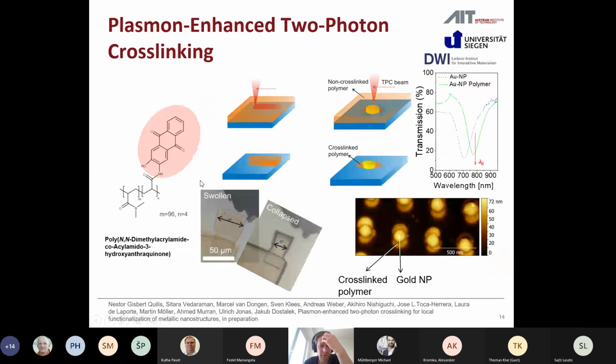In addition, this is a bit linked to what will be the next talk. We looked a bit at how the two-photon process could be used for the cross-linking of these polymer architectures with a precision which is at the nanoscale regime. We explored how to use, for instance, the enhanced field intensity associated with the resonant coupling to localized plasmons to efficiently cross-link the polymer networks only within certain sub-areas around these gold particles, in the zones referred to as plasmonic hotspots. Eventually this could be used to selectively attach the biomolecules to the most sensitive parts of the structure and push the sensitivity even further.